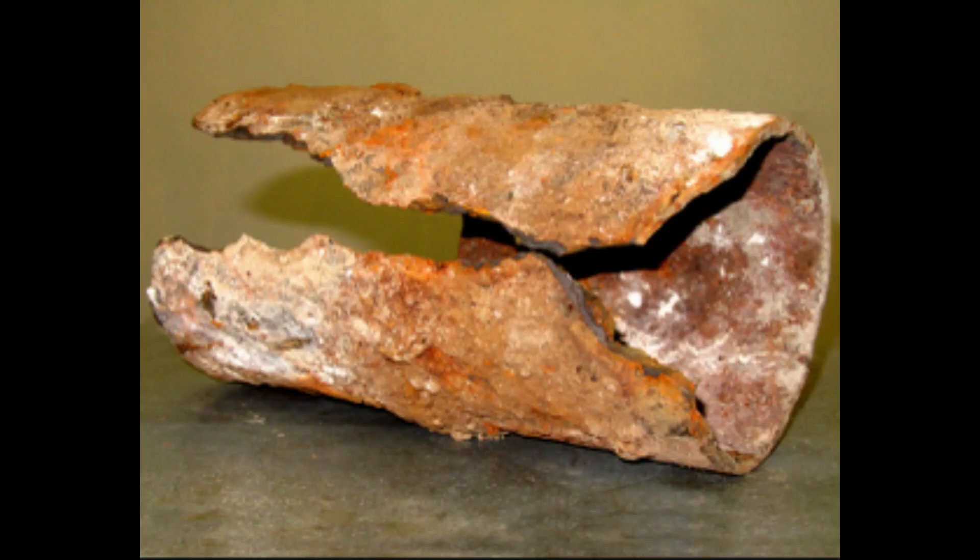That's where it rusts the fastest. When the rust gets so thin, the pipe cracks and it actually forms a wider crack with serrated edges like a knife along the bottom. Those serrated edges will catch on debris and cause repeated backups, because as you catch debris on those edges, more debris gets caught up.